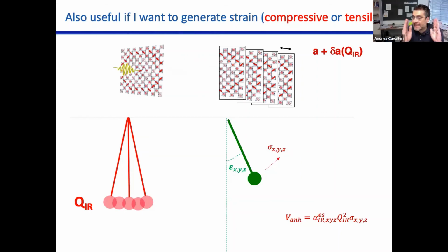But once again, when you think about increasing the temperature of a material and understanding why the material compresses or expands, it's this coupling. You have all the thermally excited phonons, which are rectified because they come in squared, and then couple to an acoustic phonon, which then increases the volume. So it's exactly the same thing, except that here it is done non-thermally by selective excitation of Q_IR. I hope this is clear enough.